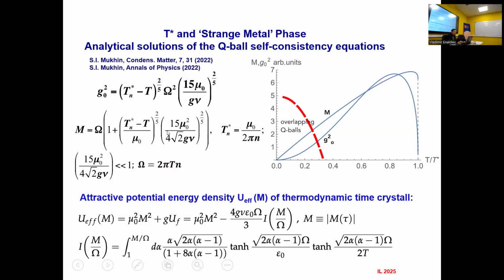Now what is also important here, so please notice that when we go away from T star and into the region where this term becomes negligible with respect to 1, because G is here in the denominator, M becomes linearly temperature dependent, which is important for us. So there would be a region of linear temperature dependence of the amplitude of the Q-ball deformation, Q-ball fluctuation.